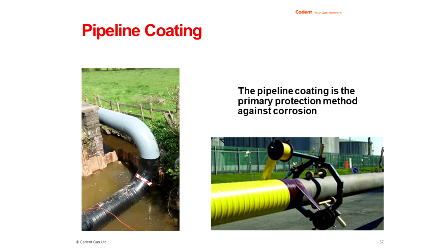So as many of you are probably thinking, if you've got your pipelines coated, then where's the requirement for cathodic protection? Well, no matter how well a pipeline is coated, there's always going to be deficiencies in it somewhere along the line, whether it be at the valves or flanges or anywhere that's awkward to coat or apply a decent wrap to the pipe. So that's where cathodic protection comes into play. At these small locations and defects in the coatings is where the CP will protect the pipe from corrosion.